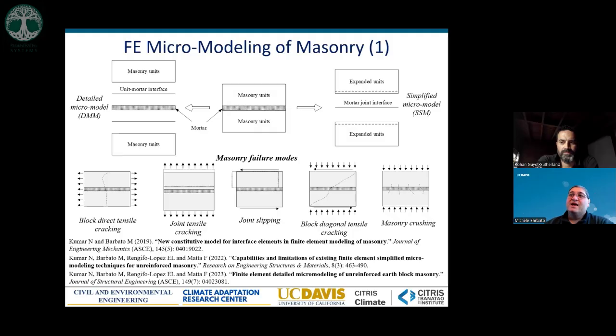And typically for ordinary masonry, there is an approach that is called the simplified micromodeling, where the blocks are expanded. The mortar joint is represented by a zero thickness model that is called the interface element. And so the interface element accounts for joint slipping and part of the cracking for tensile effects, while the blocks typically account for the masonry crushing or the direct tensile cracking.